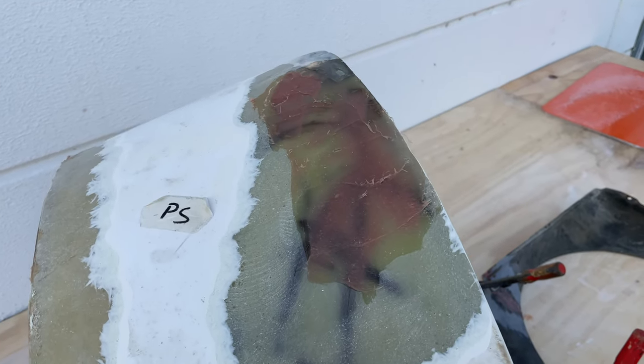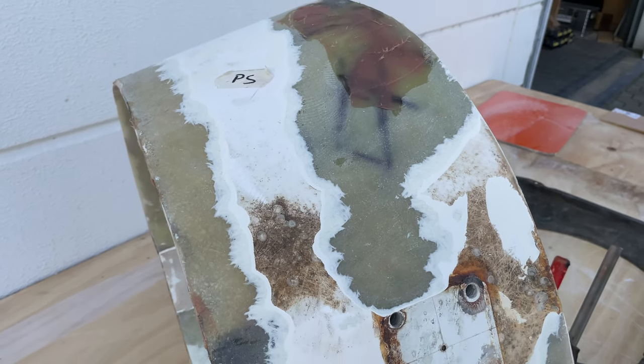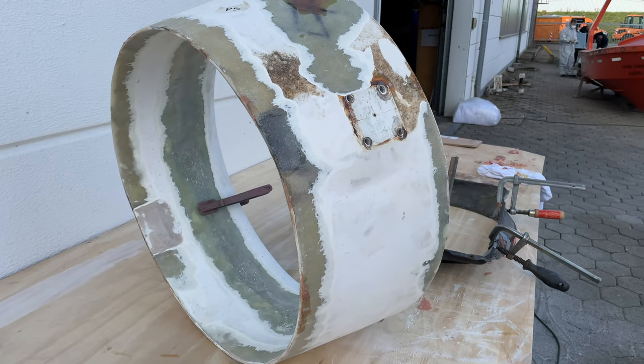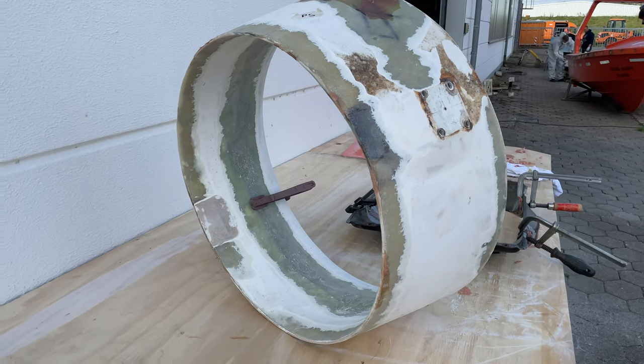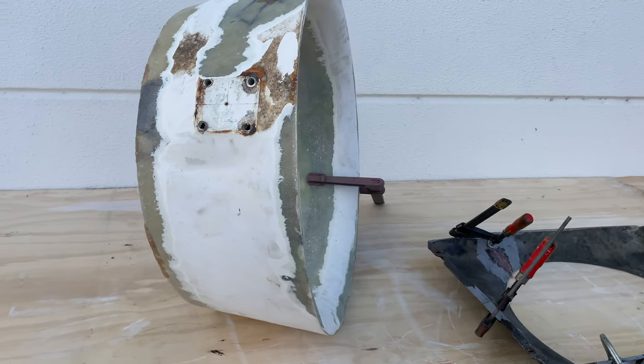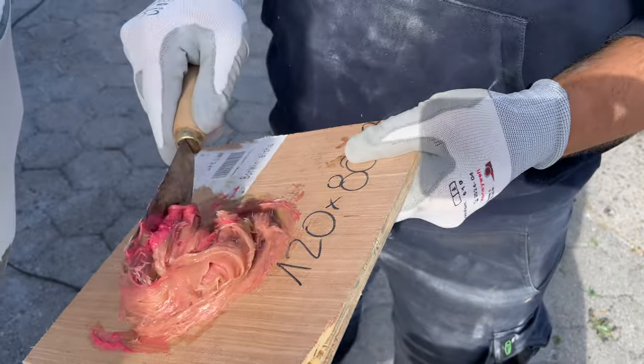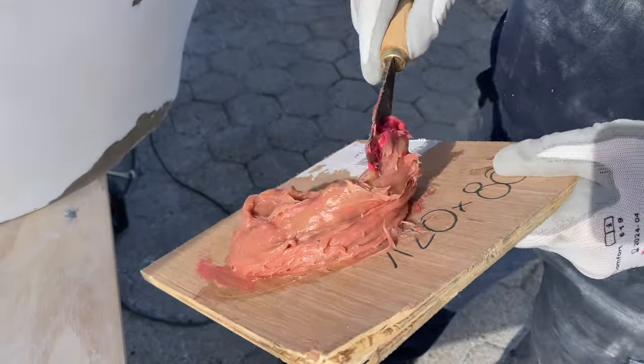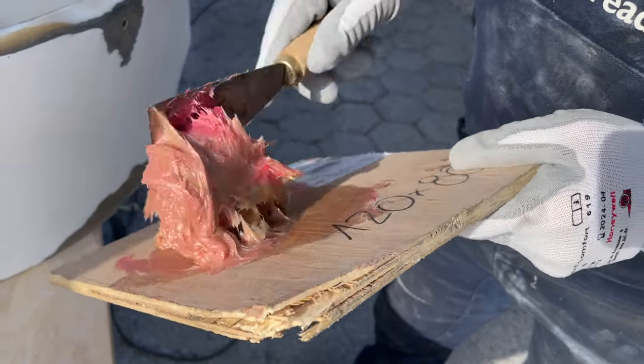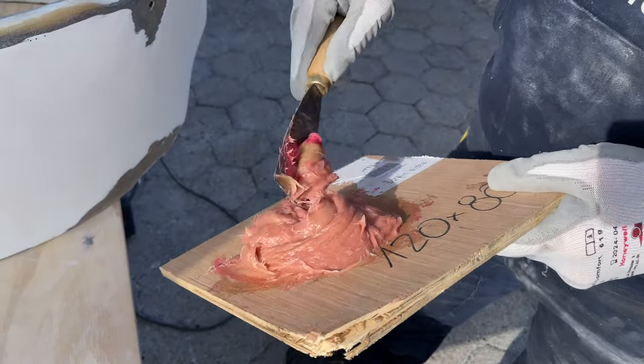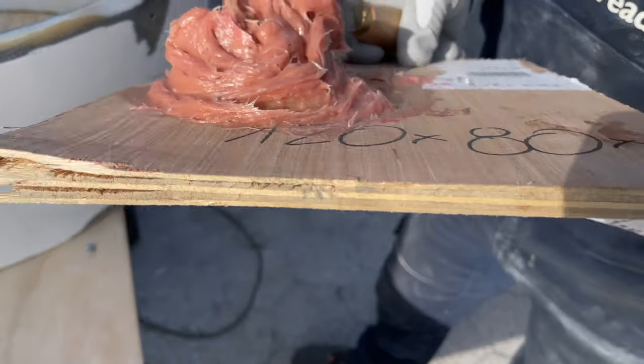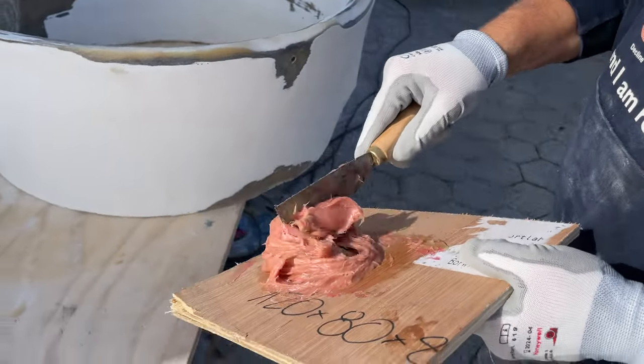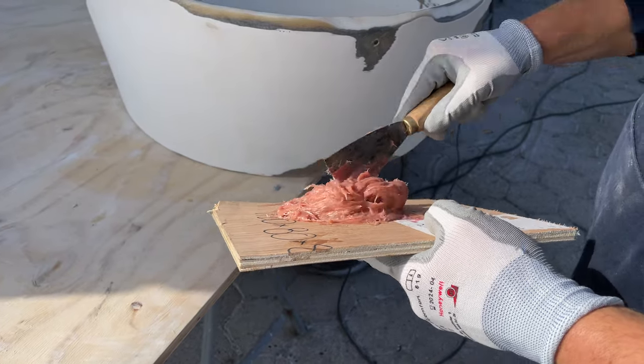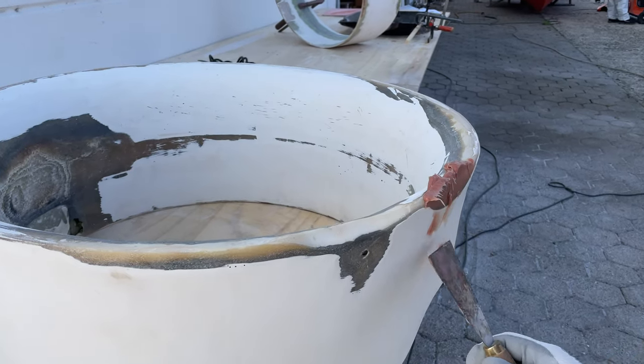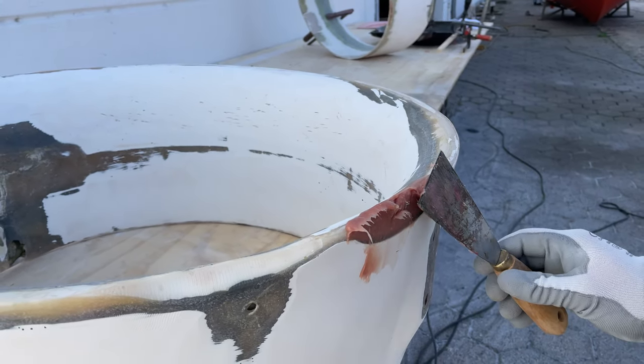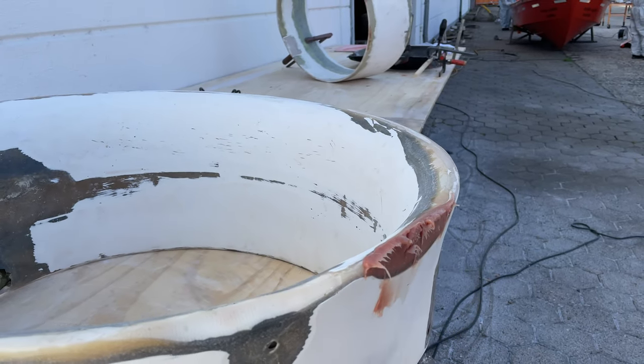So this was a fiber resin that the shipyard has in their shelves. So basically it's polyester resin with glass fibers in it. So we used that to fill all the bigger holes and the major cracks that we couldn't grind down completely. When working with polyester resin, the hardener is only a catalyzer. That means it's not as critical as it is with epoxy resin to have exactly the right mix. Nevertheless, how much hardener you put in there will significantly influence how long you have to work with the material. So you should either stick to what's in the technical data sheet or change it slightly so that it fits your needs.